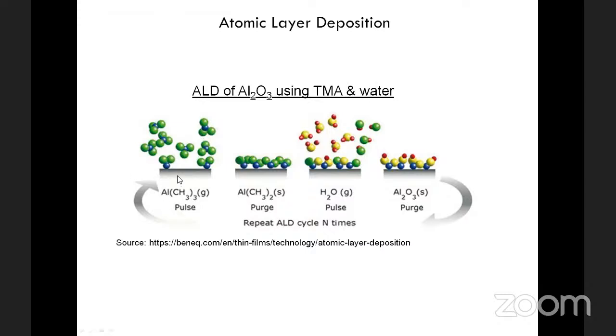And the idea is that the surface is exposed sequentially to trimethyl aluminum, purged, so only one monolayer is reacted, then exposed again to water. The unreacted methyl groups are hydrolyzed, and at the end of this sequence, we have one monolayer of aluminum oxide. Now we can repeat this cycle, and by splitting the reactions between TMA and water to sequential reactions, we can grow the oxide film incrementally with atomic and molecular level precision.